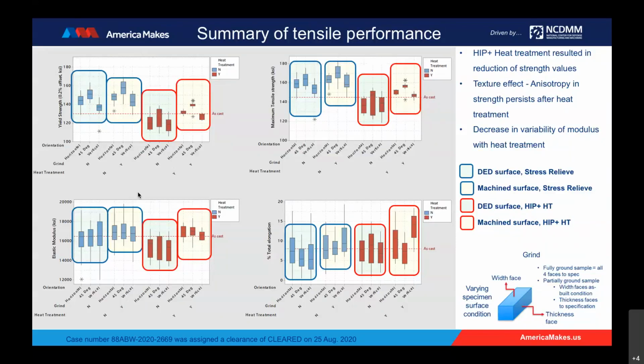So comparing this data with reference to as-cast values from the ASTM handbook, the red dotted line here are the handbook as-cast values for reference. So one of the biggest takeaways here is the anisotropy in strength performance with different test orientations, with 45-degree orientation relative to the horizontal being the largest. And the heat treatment effect is also apparent here. So upon heat treatment, we see a substantial drop in median strength values. However, the anisotropy in the material doesn't appear to be completely eliminated.